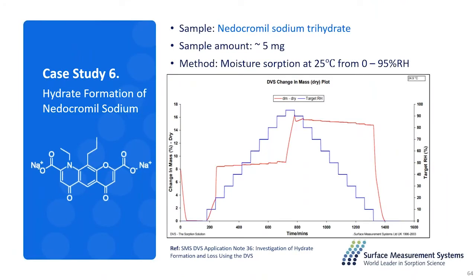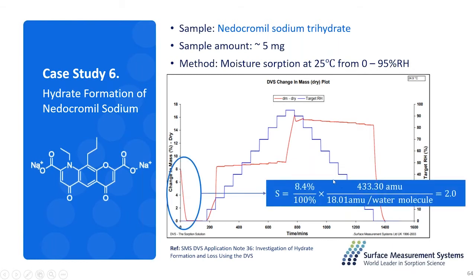And I do have a case study here for the nedocromil sodium that we use, about 5 milligrams of the sample, to perform the moisture sorption at 25 degrees. So we start the sample as a trihydrate form, and during the drying step, it's losing about 8% of moisture content inside the material, which indicates about 2 moles of the molecule is losing from the drying step. So it's forming from a trihydrate form into a monohydrate form at the drying step.